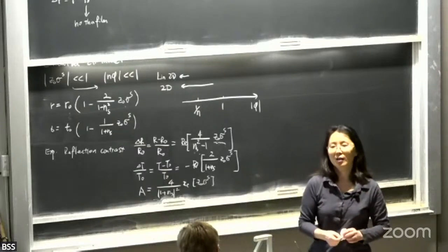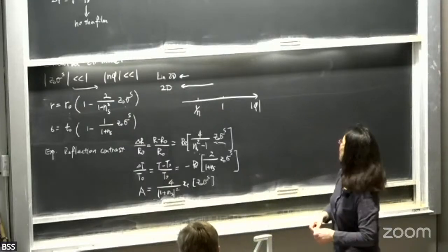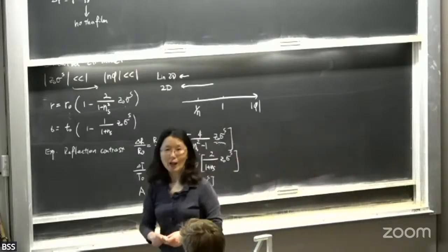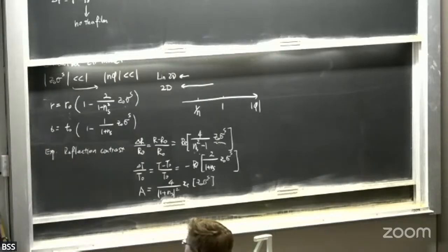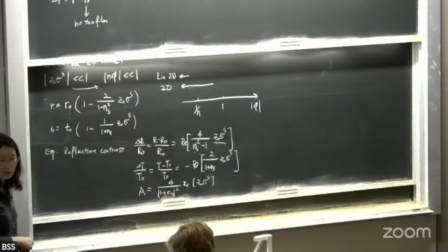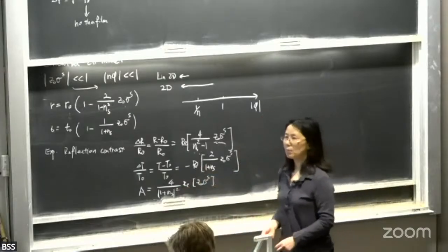Could you maybe remind us what are the typical values here? Okay, yeah. So for substrate, well, N of course is frequency dependent, right? So for transparent substrate, like a silicon oxide, for a very large range, N is about 1.5. For the materials we are talking about, it could be 3, 5, or something. So 1/n isn't that small. 1/n is not that small. Okay, so that's kind of the strategy people can use.